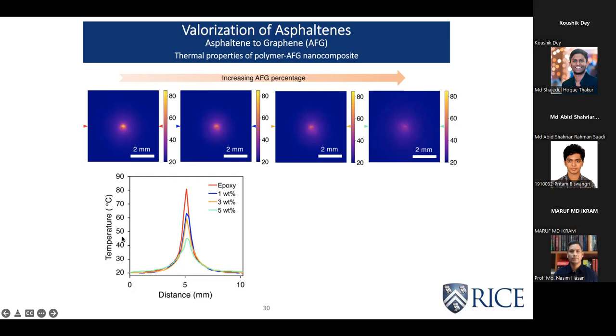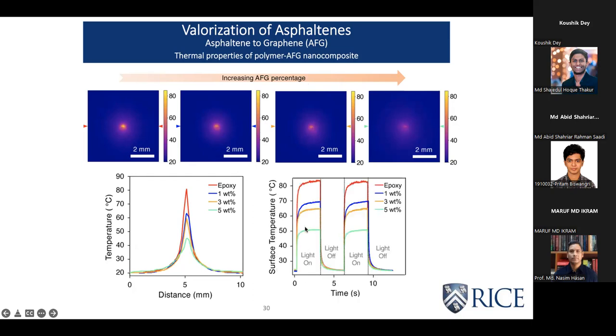This means that the material is able to dissipate more heat as we increase the graphene reinforcement percentage. We did the time-dependent study also. Basically, we kept the light on and off, on and off, and we kept recording the maximum surface temperature, and we saw a similar effect in the temporal test as well. But this test gave us the idea about the thermal dissipation behavior. We wanted to see if we can calculate the thermal conductivity from this test as well.